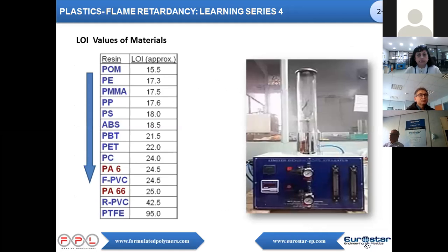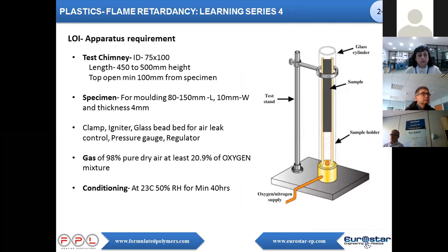For the LOI test, we require a glass chamber or chimney. The dimensions of the gas column: height will be 450 to 500 mm, and inner diameter 75 to 100 mm. The test specimen can be any type: molding, cut piece, sheets, etc. A specimen of 80 mm length, 10 mm width, 4 mm thickness is used in this test.